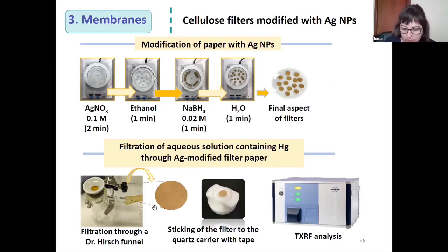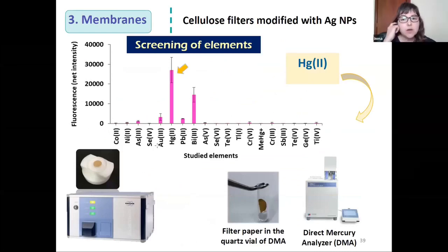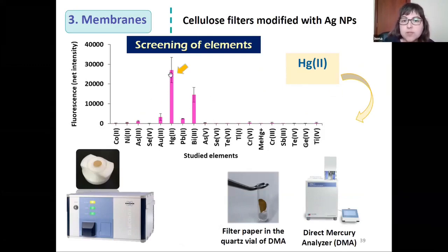In this work, we can also see how the filter with nanoparticles is stuck to the TXRF carrier before the analysis. Here, we use the TXRF as a screening of the elements. It means that we perform the filtration of different elemental solutions, and we can see here that, for example, in the case of mercury, we observe a better signal, allowing that the mercury can be trapped by amalgamation into these filters. Since the direct mercury analyzer, DMA, provides a better sensitivity, which is specific for mercury, we perform the work only with DMA, but we use the TXRF for this screening.